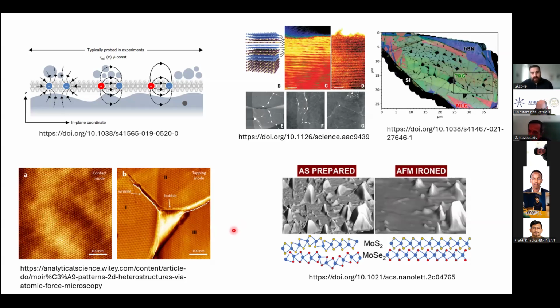There are ways to fight it, like using an AFM tip to iron your sample and push away things. You have to be extra careful to do that because you have to use a very soft tip to not damage your substrate, your material. And you can also use maybe thermal annealing, thermal energy to move away all these air pockets and the adsorbents. But high thermal energy is kind of dangerous because it's been reported that it relaxes a little bit the twist angle. So if you design your moiré heterostructure and you want a 3 degrees twist angle, and you increase the temperature a lot to create a homogeneous heterostructure, you might deviate from this twist angle and you might lose the properties that you aim for.